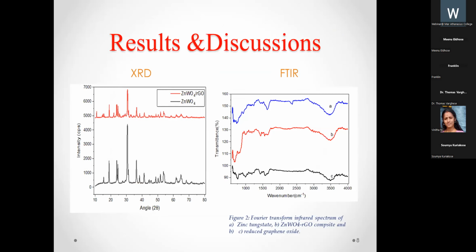Moving on to our results and discussions, here I have shown the XRD of both zinc tungstate and zinc tungstate RGO. I have only included the 4% result of XRD because that is much more electrochemically active. The first one represents the XRD pattern obtained for zinc tungstate, and the second one represents the XRD pattern obtained for the zinc tungstate reduced graphene oxide composites.